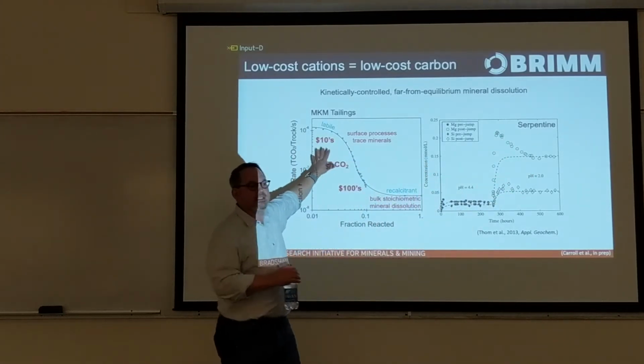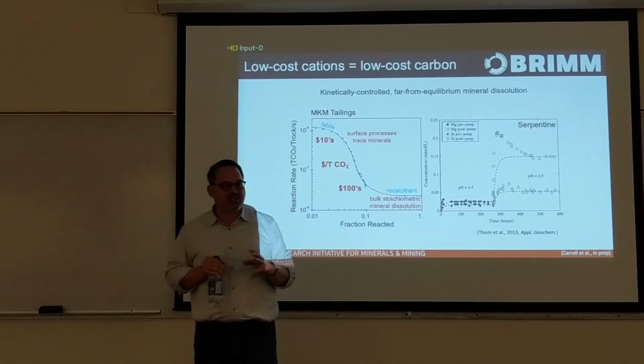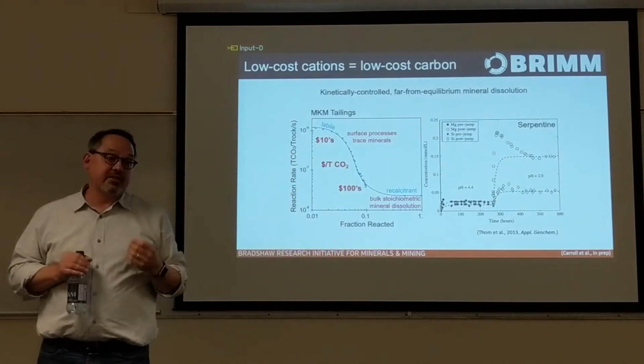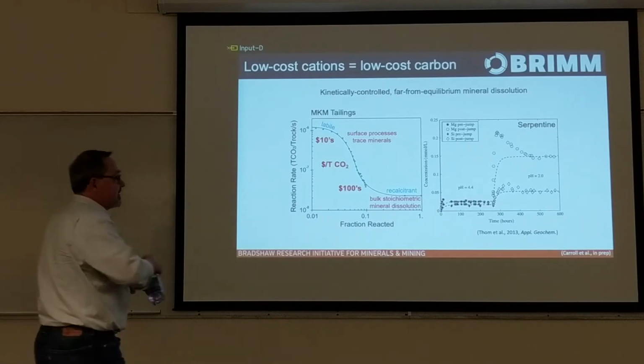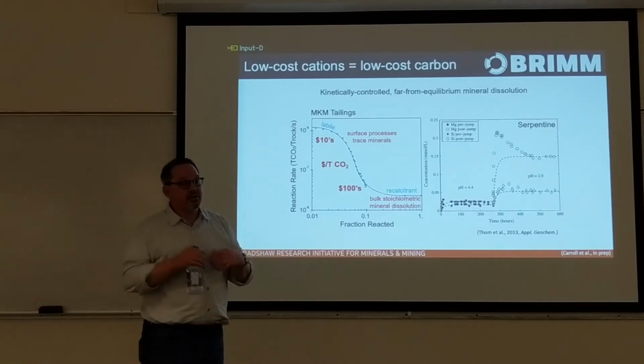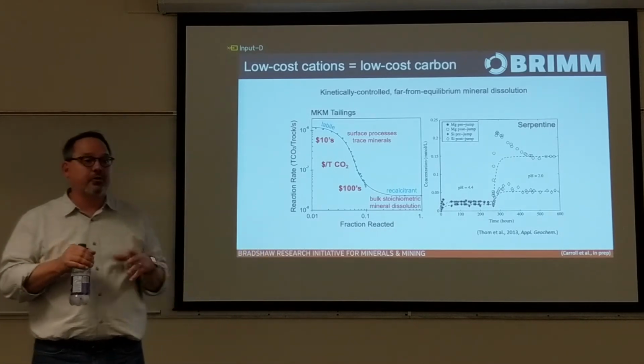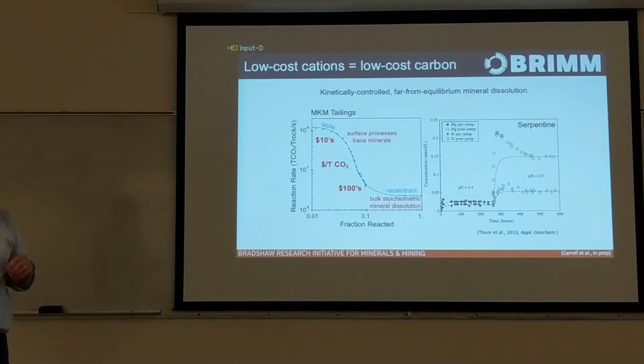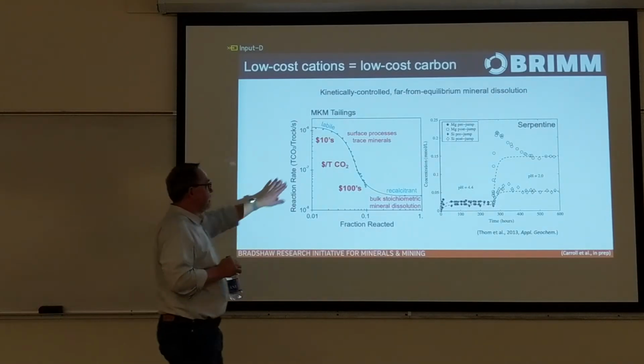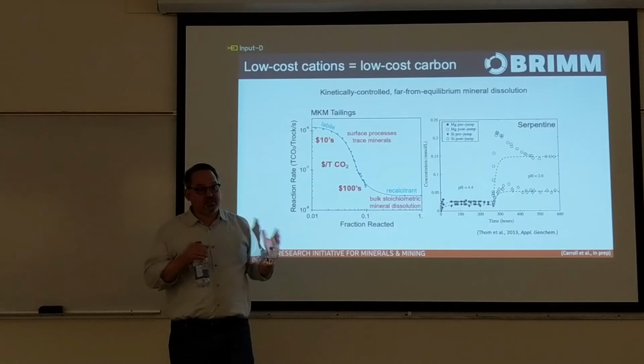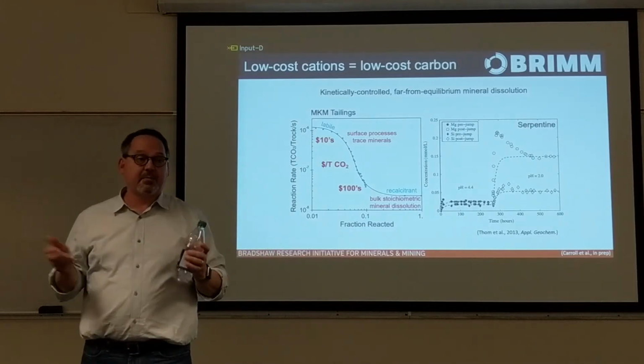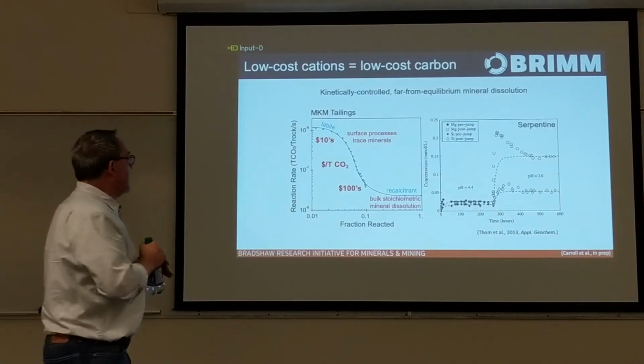So some of this fast release magnesium is surface processes on silicate minerals, especially clays and serpentine, which have a high intrinsic surface area. So even if you're only reacting 1 or 2 layers of the mineral, it can actually affect a significant amount of the magnesium budget because the surface area of these minerals is so high, especially when they've been crushed.